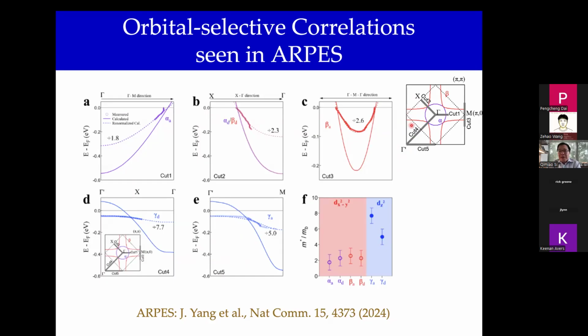red one here, which are primarily, sorry, the color is a bit off, these are the z square states. And so the numbers here give, or the inverse of that is, the renormalization factor. You can just use these numbers. And so experimentally, it's clear that indeed z square orbitals have stronger renormalization. Experiment is also showing that in this material, at least, the z square band has sunk below the Fermi energy.